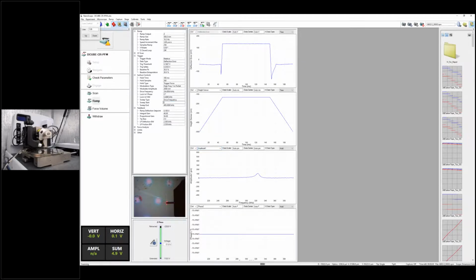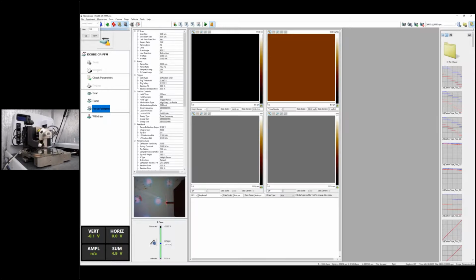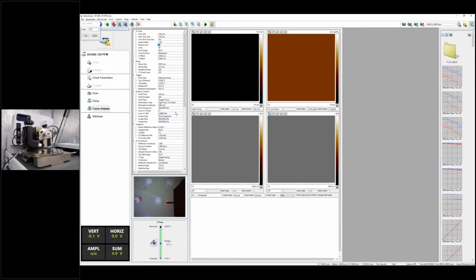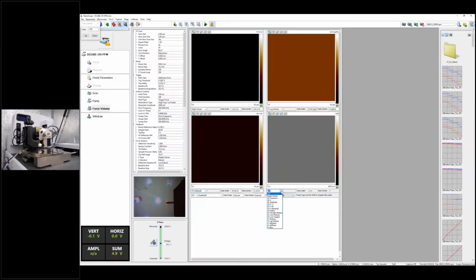So I can further narrow this down, maybe from 300 to 380. Yeah, so we can still cover this peak within this range, which is good. Slightly increase to make sure my peak is relatively in the center. Okay, so once we've done this, we can move into the DataCube part. So I'm going to increase the resolution a little bit. And I still use this frequency range for my sweeping, and all the other parameters I don't have to care about right now. So I want to see the contact resonance amplitude, which is amplitude at the contact resonance frequency, and maybe I can also check the frequency change.